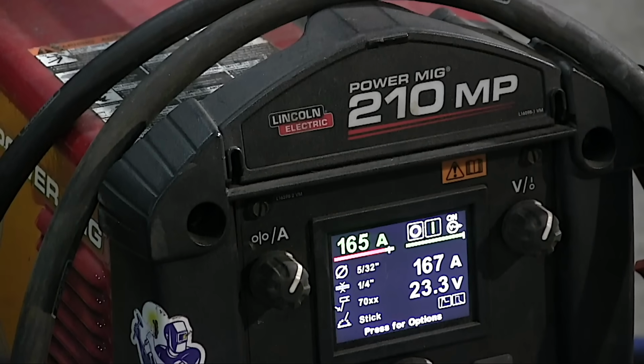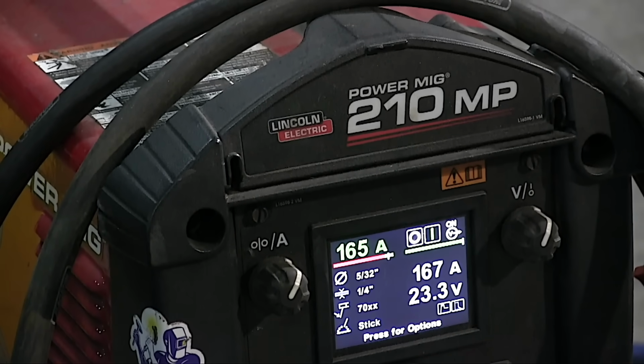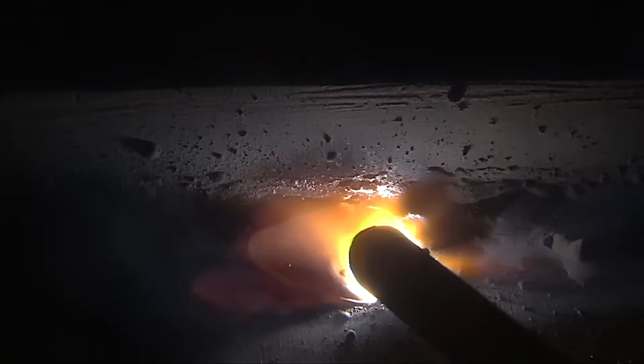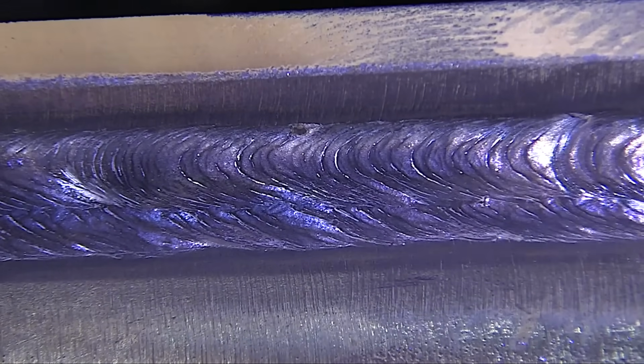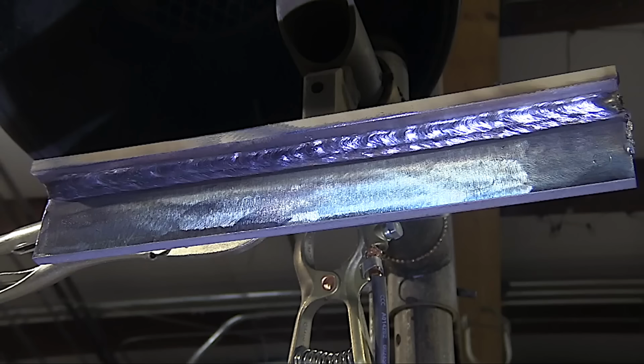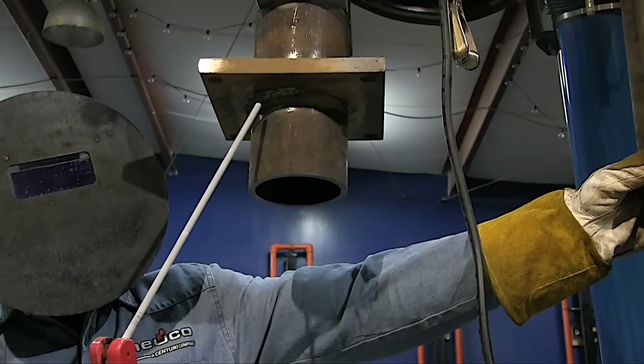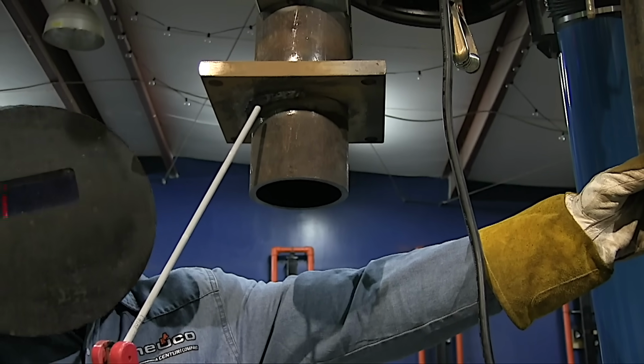This is my friend Andrew Carden, 165 amps here with a 5/32 7018, and we're using up a lot of used rods, so stubs, so it's like a ton of tie-ins on this joint. It's a 3-pass overhead T-joint. We're using a nice tight arc with not much rod angle, good hot amperage, and by using all those rod stubs, we've got a lot of practice with restarts on this weld. And there's a ton of restarts there, but you can't really tell it too much. Practicing your restarts is fundamental to stick welding.